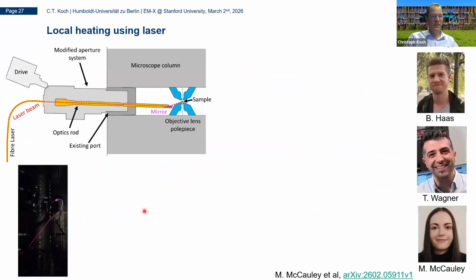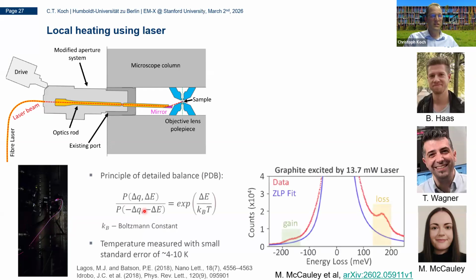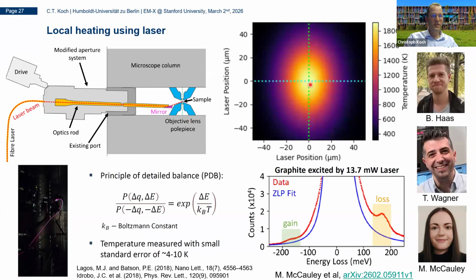And that actually reduces the amplitudes of the displacements, but the directions of the displacements, we've checked this, actually are preserved. So of course, one can combine this now with heating experiments where you change the temperature and then see basically how higher order modes are also excited, or more strongly excited. So we have recently done some laser experiments in this same microscope where we now shine a laser onto our sample and produce then maps of the local temperature. And this can be done by the principle of detailed balance.